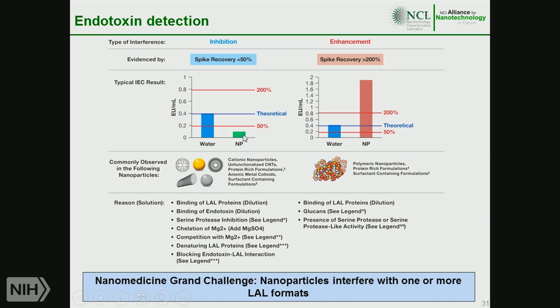But in this case, we are using colloidal gold nanoparticles. We spike the same amount of endotoxin, and now we detect about 0.1 EU instead of 0.4 EU. So this is inhibition. It's less than 50%. In this case, it was polymeric nanoparticle. Instead of 0.4 EU, we now detect 1.8 endotoxin units per mil. So it looks like this material contains a lot of endotoxin, but in fact, this polymer behaves like endotoxin in the LAL assay. And this inhibition is very common for cationic nanoparticles, unfunctionalized carbon nanotubes, protein-rich formulations, anionic metal colloids, and surfactant-containing formulations. And enhancement is very common for polymeric nanoparticles, and depending on the concentration of protein and surfactant, it can also be observed in protein-rich formulations and surfactant-containing formulations.